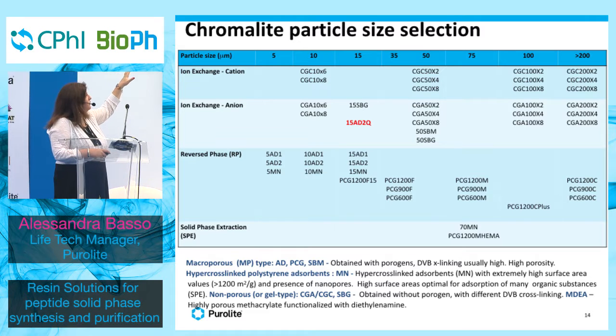So I will show you some examples of the reverse phase, the AD and PCG products. You see in the first line, they are macroporous, very strong, robust, with good porosity to allow the permeation of molecules such as peptides. Whereas we also have the ion exchangers that are used for peptides when you have to do purification of peptides by ion exchange, and I will show you the acetate form. The new entry in red, we are quite proud of this, so we are now developing a full line of ion exchanger products in 15 and 10 microns. If you are interested in testing, this is the new entry, the 15AD2Q, a quaternary amine, very useful for purification of peptides through ion exchange.